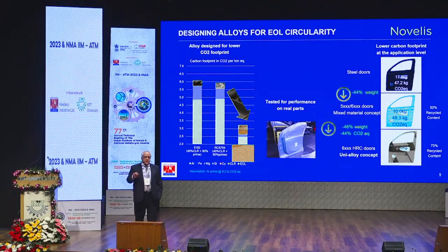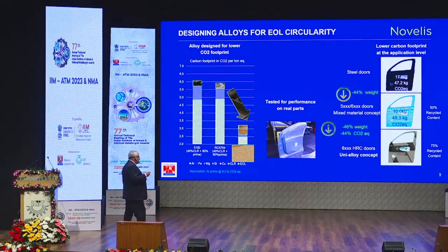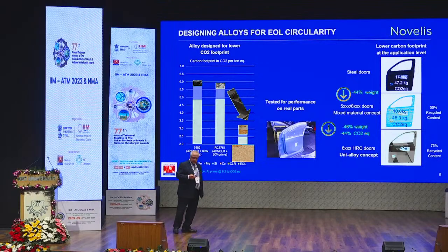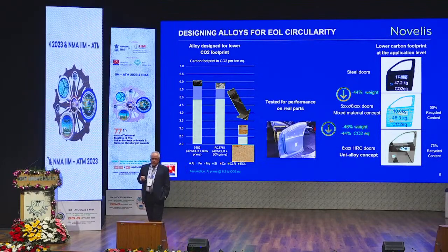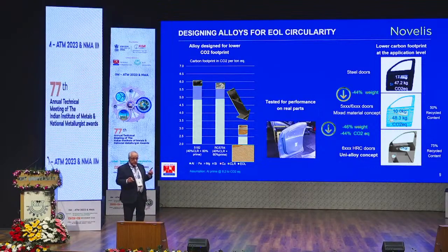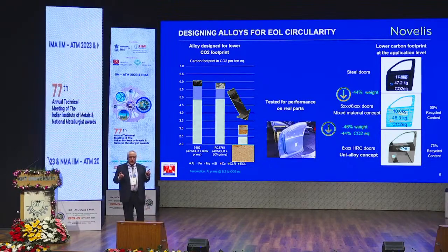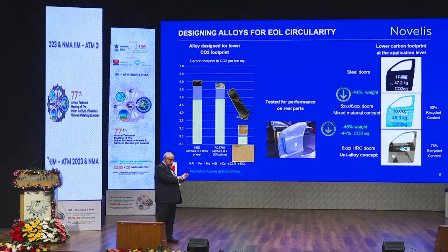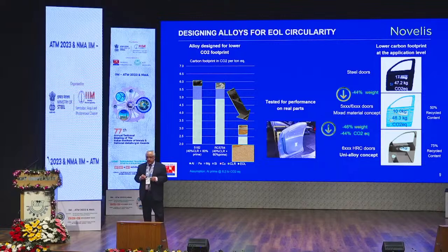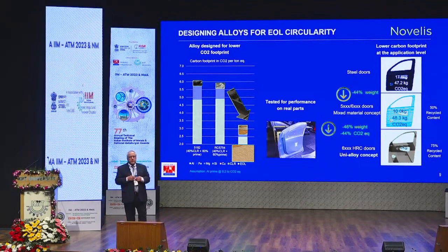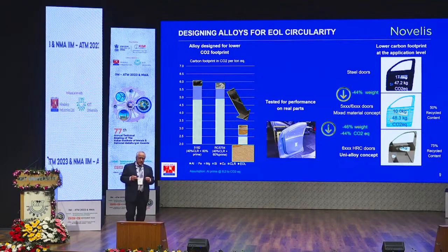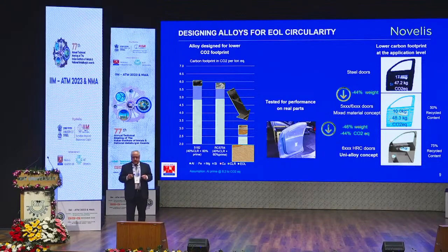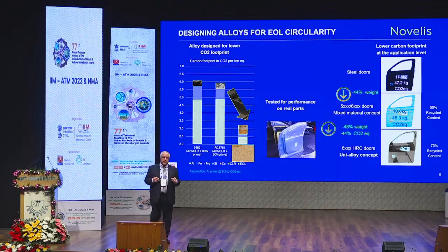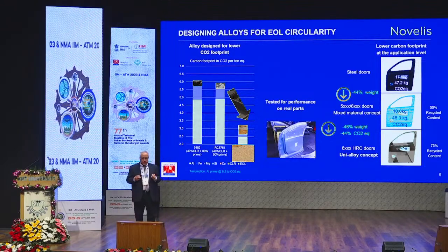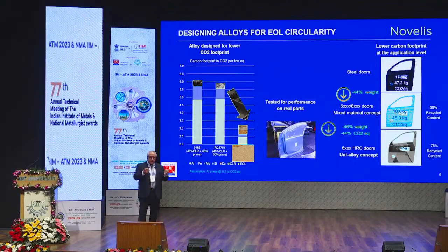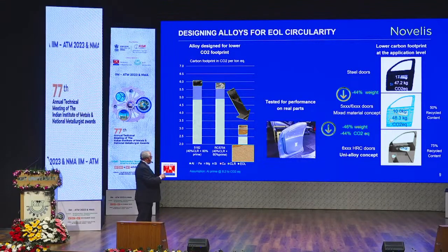What does it mean then in terms of performance? If I take the example of a door, you will hear this number several times, as compared to a fully optimized steel door, if we move to aluminum solutions, we save 44% of weight. But if we do that with the 2 alloys, the 5,000 and 6,000, unfortunately we are not better than steel in terms of CO2. When we go to this new generation of alloys with much higher content of end-of-life scrap, we bring the CO2 footprint down. And in this case, thanks to the performance of the alloy, we have a little bit better weight saving, about 46%, but we have also a 44% reduction of CO2. So you see how important the metallurgy is, and the metallurgy in link with the understanding of the scrap market and the monitoring of the scrap market.